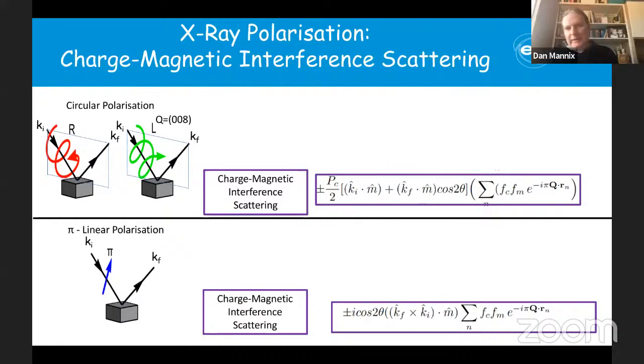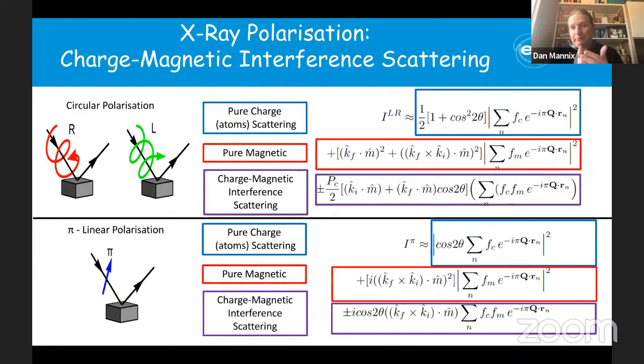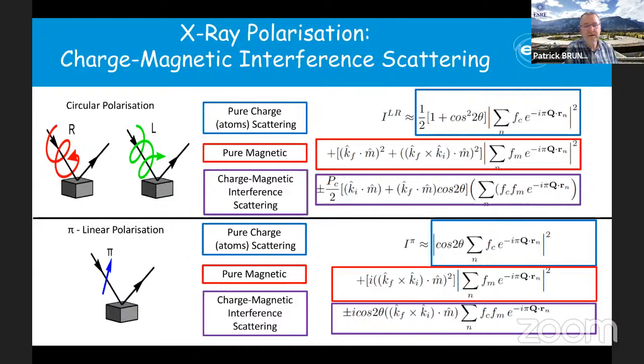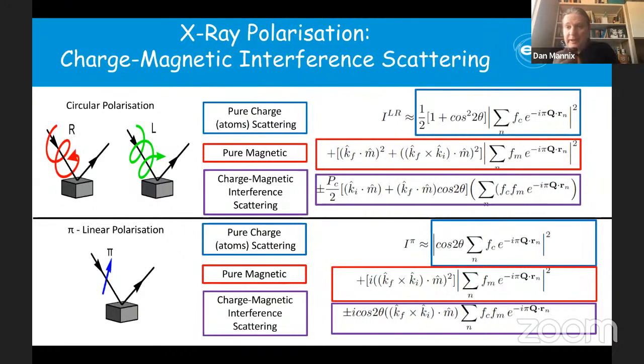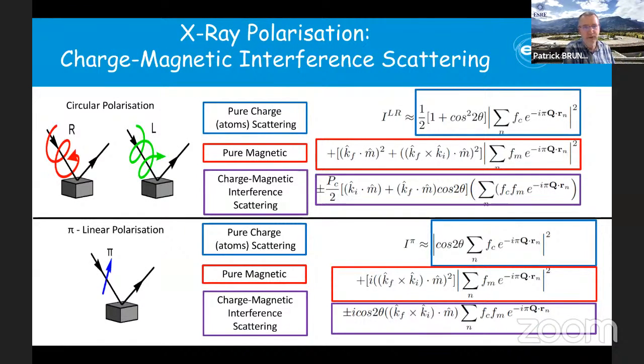Yes. So I believe that what we haven't done in those experiments was really explore more Bragg peaks and go around different Bragg peaks, and then you can in principle predict what your contrast should be, because especially with this FDMNES code, we know pretty much what it should be. By going to different Bragg peaks, you could get that. We just didn't get time to do it in the original experiment. Okay, so you can get more information about which domains you are looking at by doing this at different Bragg reflections. Yeah. So Guillaume Bettier says, I was talking about circular light, but that's what you are just showing here on the slide, I think, on the top part of this. Yeah. That should answer the question, I hope.